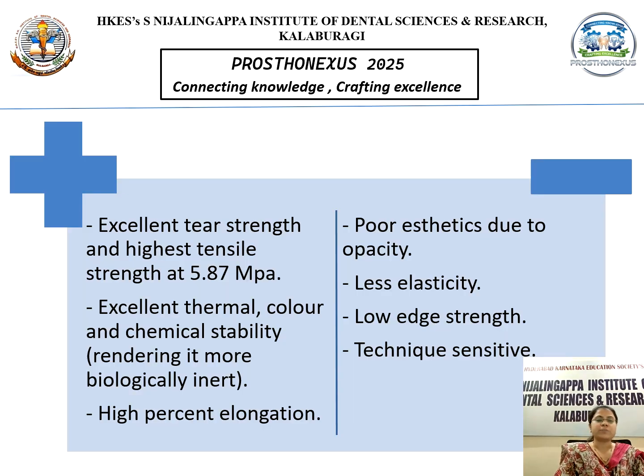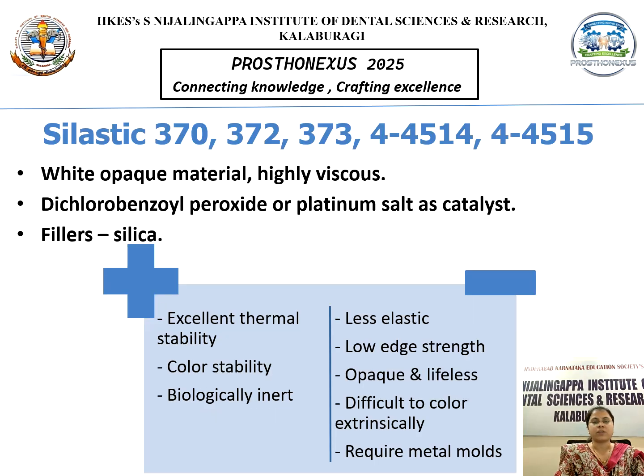The advantages of this material are excellent tear strength and the highest tensile strength at 5.87 megapascal, while excellent thermal, color, and chemical stability. It has a high percentage elongation. While the disadvantages of this material are poor aesthetics due to opacity, less elasticity, less edge strength, and technique sensitivity. The Silastic 370, 372, 373, 4-4514, 4-4515.